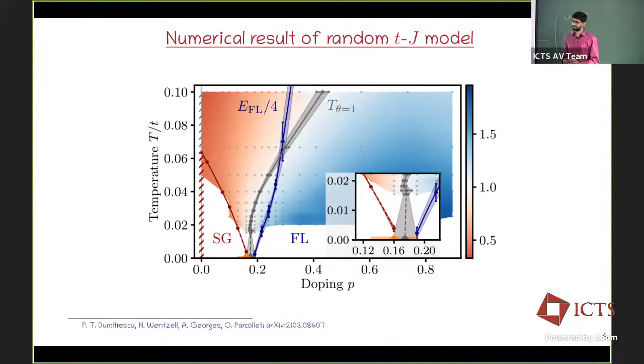So that, again, brings back the point that I think you were asking yesterday. If you look at just the single particle electron Green's function, then it's really Fermi-Liquid-like. Even in this solution, you can see that the exponent eta c is still exactly 1. It's Fermi-Liquid like. It's only the spin correlator or the spin exponent that's varying, and that's the hallmark of this non-Fermi-Liquid behavior in this kind of system. So that is really important to what you look at.